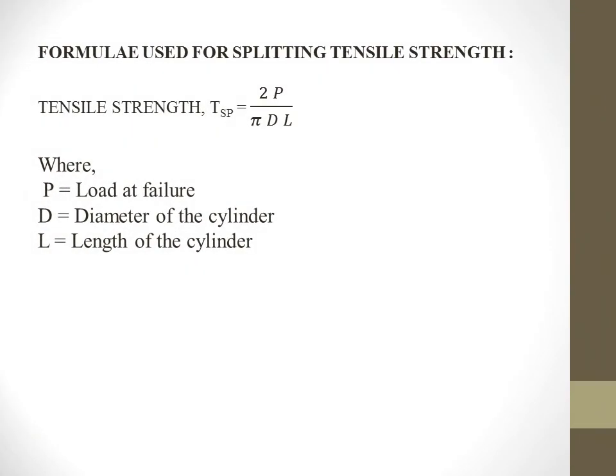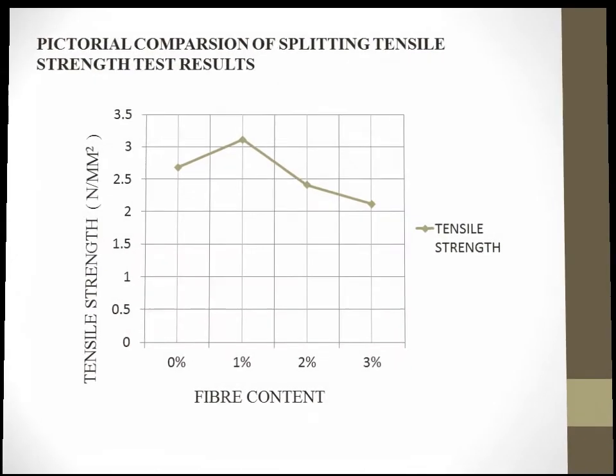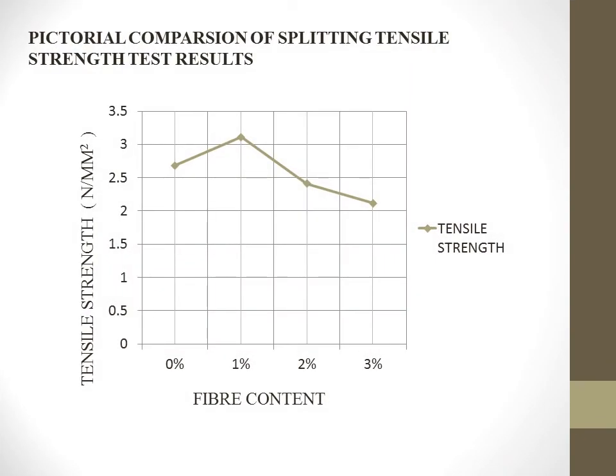This is the formula which we had used for finding out the tensile strength. TSP, which is the tensile strength, is equal to 2 times the load at failure divided by pi times the diameter of the cylinder times the length of the cylinder. This is the pictorial representation of split tensile strength test results. As you can see, there is a slight increase with 1% of fiber content, and then there is a gradual decrease with increase of fiber content.